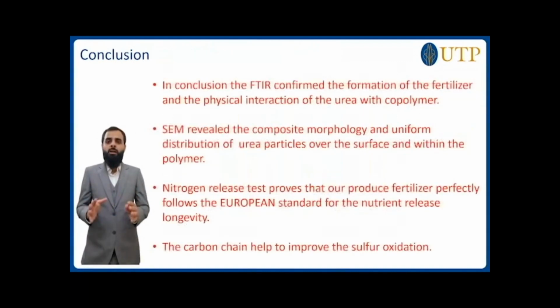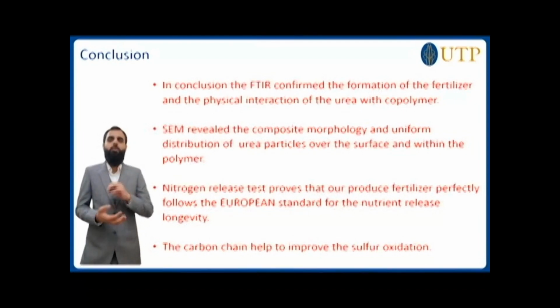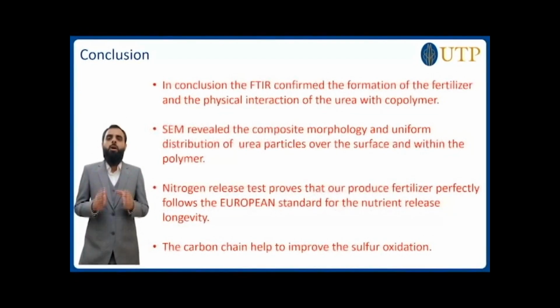In conclusion, FTIR revealed the physical interaction between urea and copolymer. SEM images revealed the composite morphology and uniform distribution of urea particles over the surface of the fertilizer and inside the fertilizer. The nitrogen release test revealed that this fertilizer perfectly follows the European standards, and it also helps to improve the sulfur oxidation, which in turn helps the plant for its growth. It also prevents the economic losses and also prevents the environmental pollution.